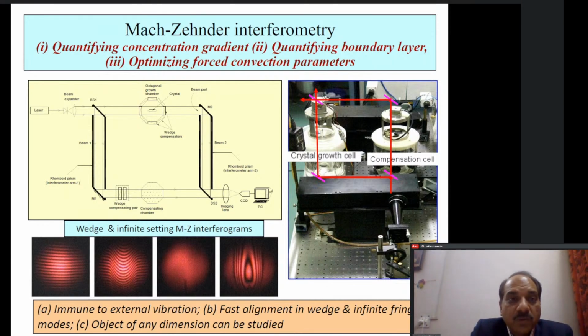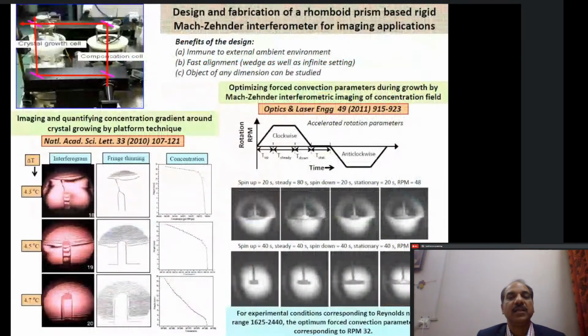This interferometry has been used for quantifying the concentration gradient about the diffusion boundary layer, or solutal boundary layer, around a growing crystal, and also we have optimized the forced convection parameters during growth of the crystal. These are some of the reference interferograms which have been captured using this interferometer. I'll not go into the details of the alignment of this interferometer. It can be aligned in wedge and infinite setting, and we performed experiments in both these settings, and the reasons for using wedge and infinite setting are different. Let me skip that part because of the less time available, and go to the crystal growth that we have done.